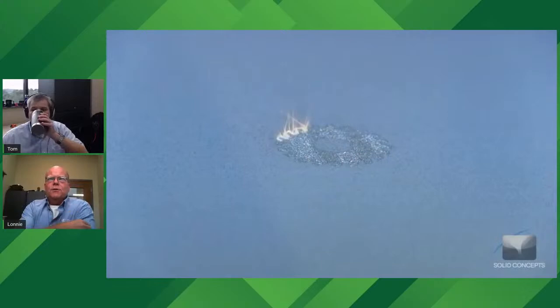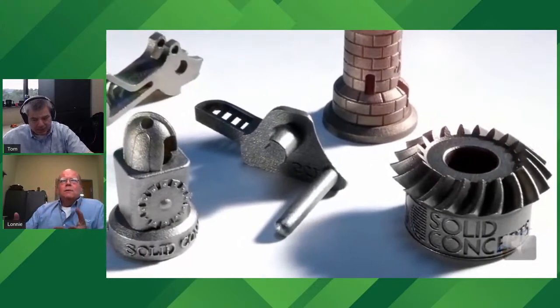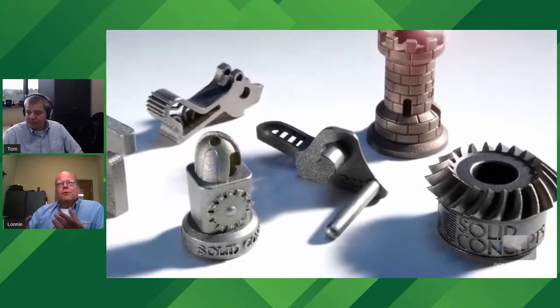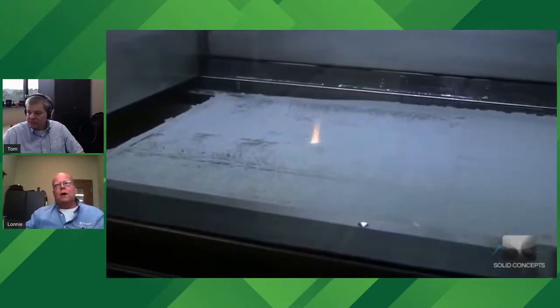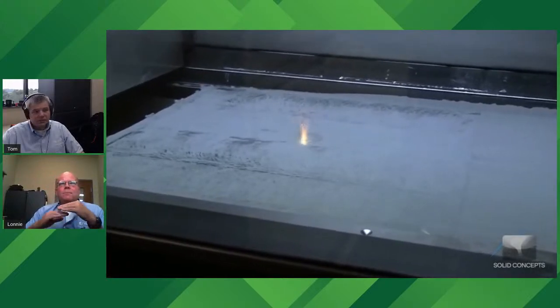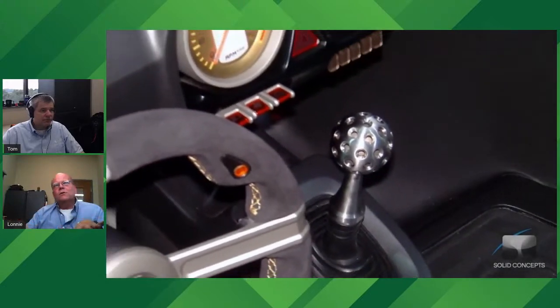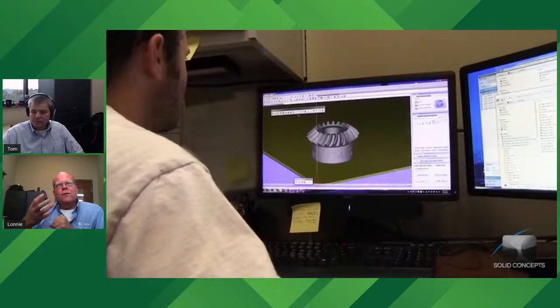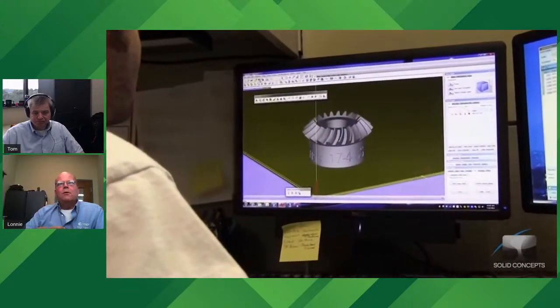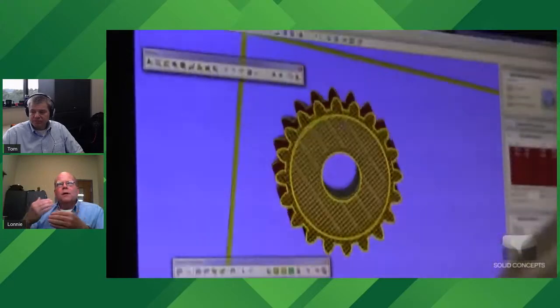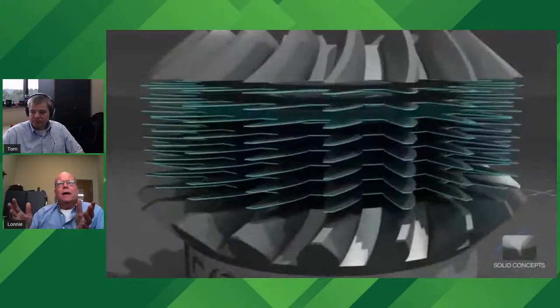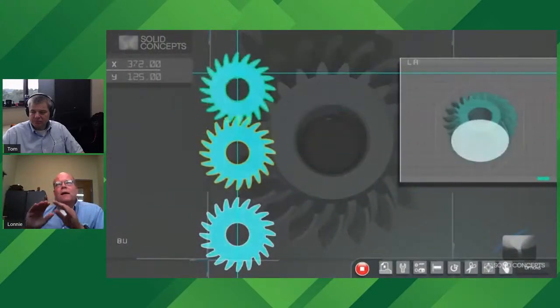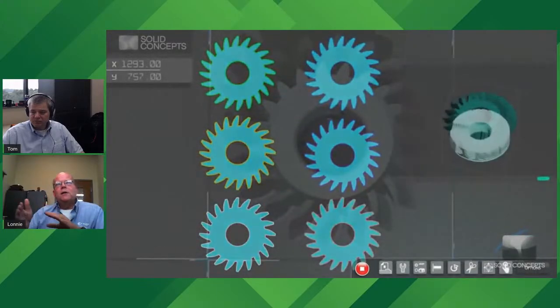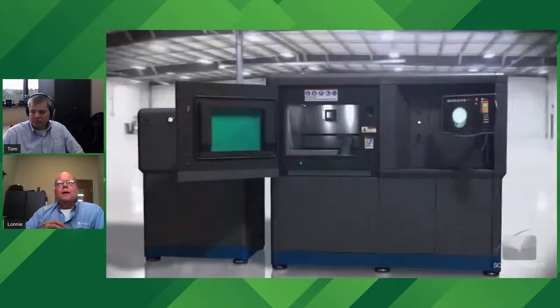One of the challenges with the laser powder bed is you're melting metal, and you're having very high temperature gradients, both across the layer and into the depth. You have these massive temperature gradients, and so that manifests itself as residual stress, which causes the parts to warp and curl. So you have to think about how you anchor that part down. You probably will need a wire EDM to cut it off. If you need really tight functional surfaces, you need to add enough material, usually 20 thousandths to 30 thousandths extra, to machine away to get to your fully dense part.